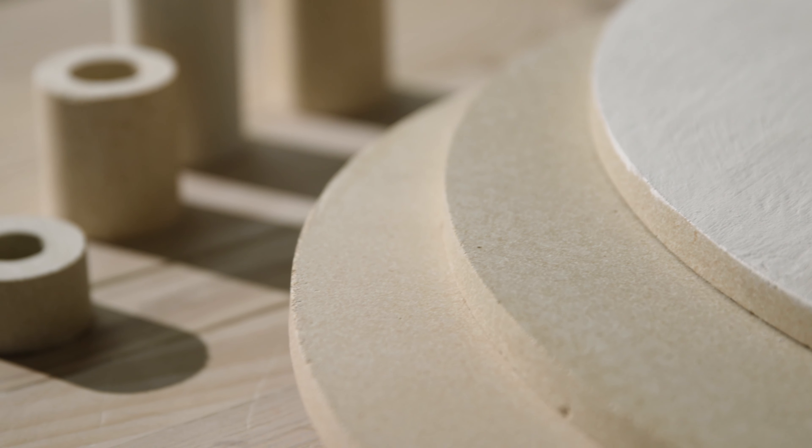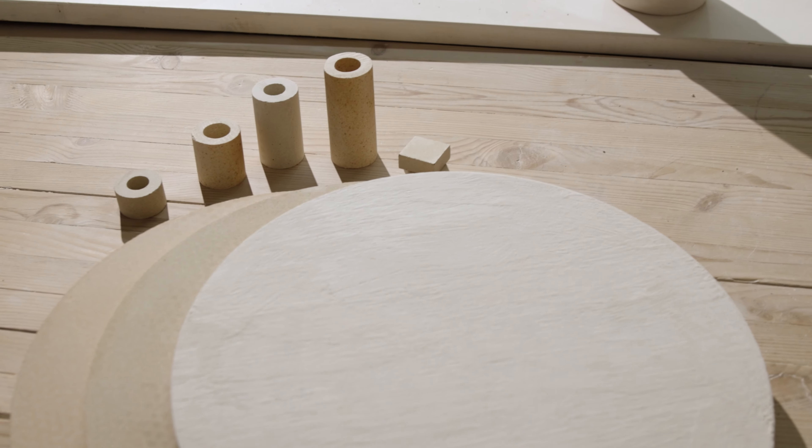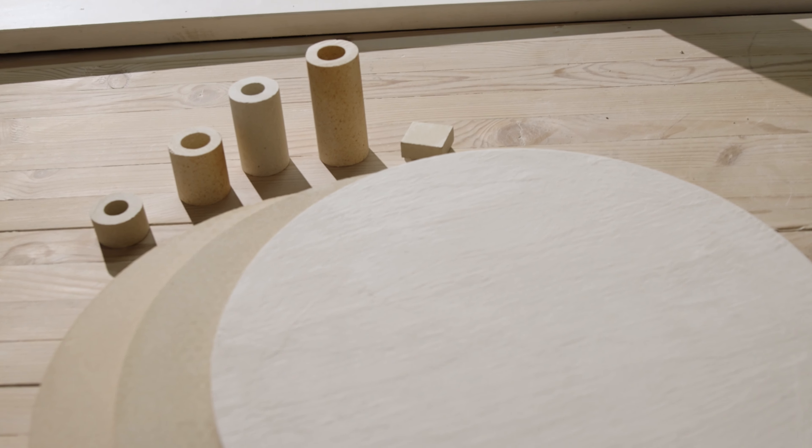The application should be opaque and even, but not thick. The colour of the bat should no longer show through. Only one side of the furniture bat is painted and your ware is then placed on this.